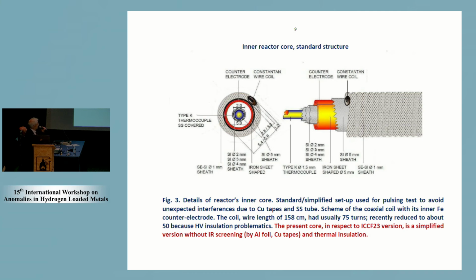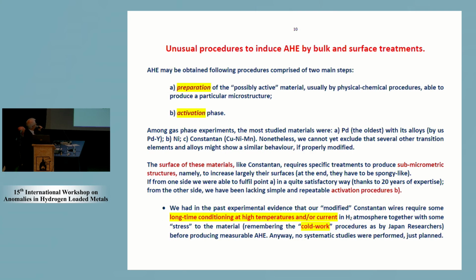In the schematic of our coil, the Constantan is put inside this glassy sheet. It has details, so now there is no time to go into them. Anyway, you can watch them more deeply. The experiment has 2 phases. One is the preparation procedure, mostly a chemical and physical procedure. The other is the activation. For the preparation, we have enough experience and we can do it quite easily.